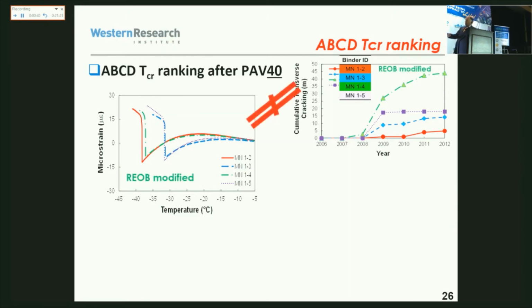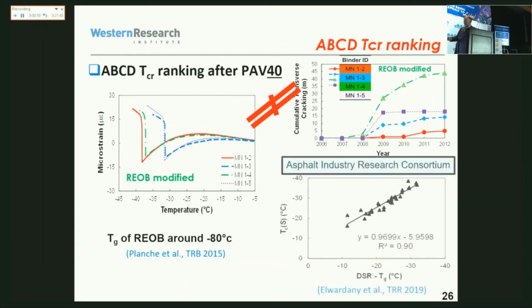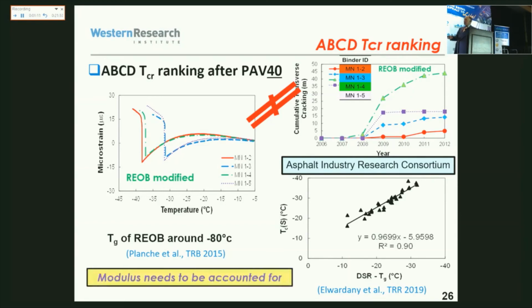We found out very easily that REOB has a glass transition around minus 80 degrees C. That's why it softens asphalt very well, and that is what this is showing here. So this test works for polymer modified, and I will show more data, but that's not the whole answer. What needs to be accounted for is the modulus itself, because with REOB we softened the binder so much that it became very, very soft, with a very low modulus.